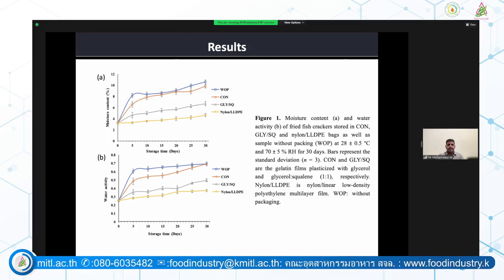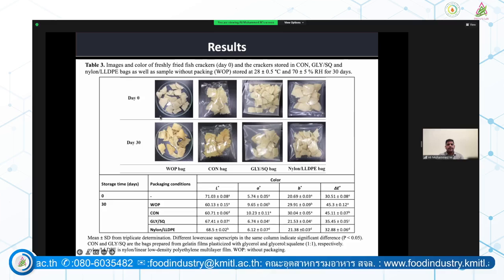And these are the color indicators. This is day 0 of the storage studies, where you can see the cracker stored outside, packed in the gelatin bag incorporated with glycerol, the bags incorporated with squalene, and the commercial packaging. And after day 30, we can see a huge amount of color change in the crackers stored without packaging and with glycerol packaging. And we can see comparable changes in the squalene incorporated and commercial bags, and similar color indications were found.